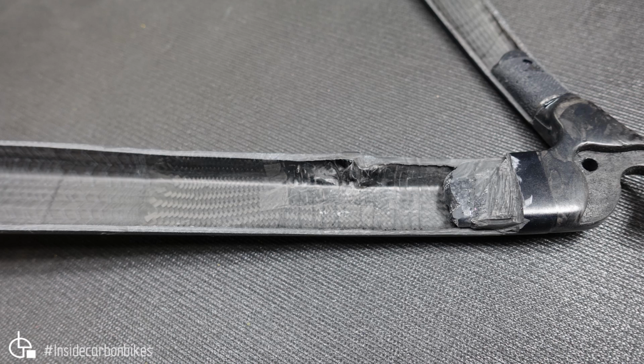So here, moving down towards the rear dropout, you can see that from about this area onwards, they've used a finer weave fabric, so it's a lighter weight fabric. They've done that because you've got a cable exit port in this region here, and that's all molded in, and it actually looks better in real life than it does in this photo. So that port's molded in. They're using a finer fabric, so it goes into those corners in a nicer manner, less likely to wrinkle and crease, and also, where the bond to the dropout is, and I'll talk about the dropout in a minute, lighter fabric can often assist you with the bond.